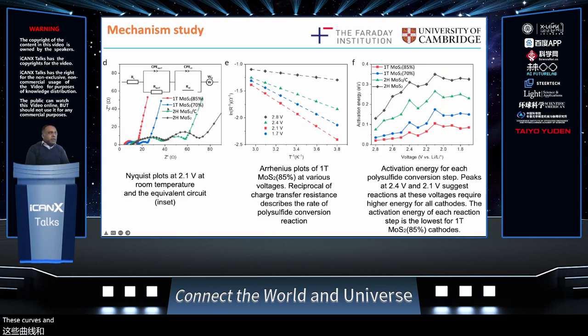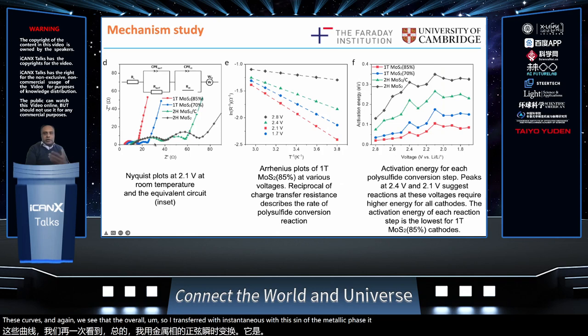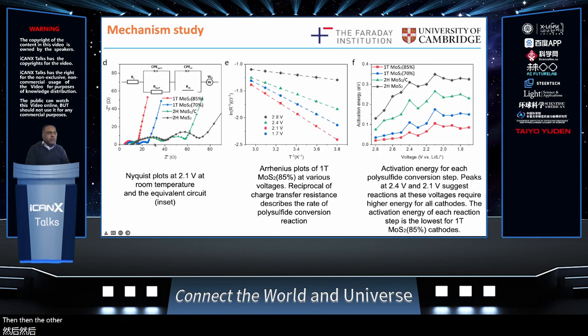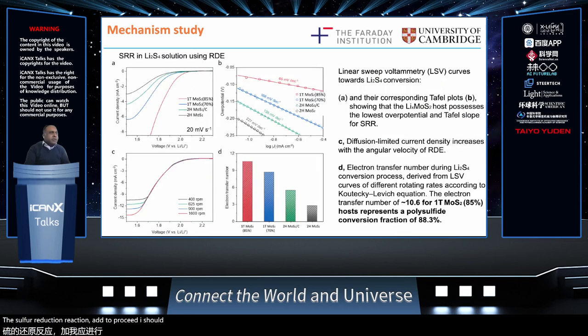And again, we see that the overall charge transfer resistance and series resistance of the metallic phase is significantly lower than the other electrodes. Now, one important parameter for the reaction to proceed, the sulfur reduction reaction to proceed. I should actually go to this figure, and then I'll come back to the previous slide.